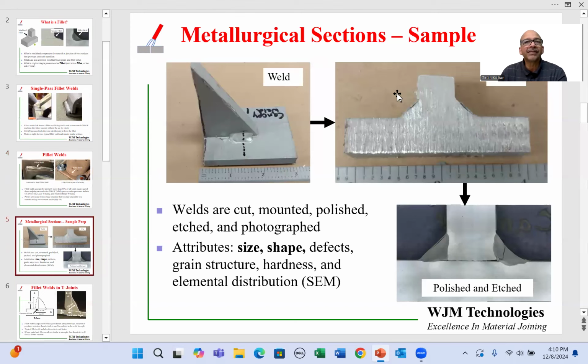So this is the process for metallurgical sections of welds. On the left-hand side, I'm showing you a component which has two fillet welds. You can't see on the other side. There's a fillet weld on one side and the corresponding fillet on the other side. And I wanted the lab to cross-section it at this location, so I marked it up with a marker and sent it to the lab. The lab proceeds by making a cut right along this line with a bandsaw. However, the cutting process with the bandsaw produces a very rough cut, and we don't see a lot of good information from that cut. So then the lab proceeds to mount the sample in an epoxy mount, polish it, and etch it. Etching is a process of treating the polished surface with a suitable chemical, which brings out the character of these welds by producing a contrast.